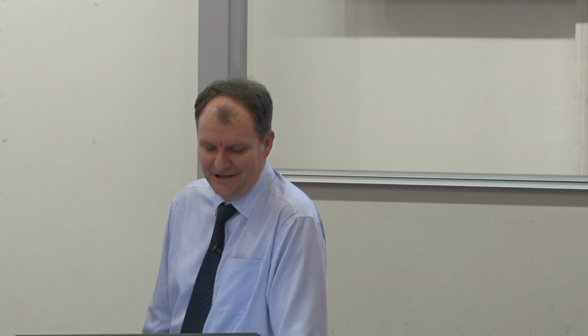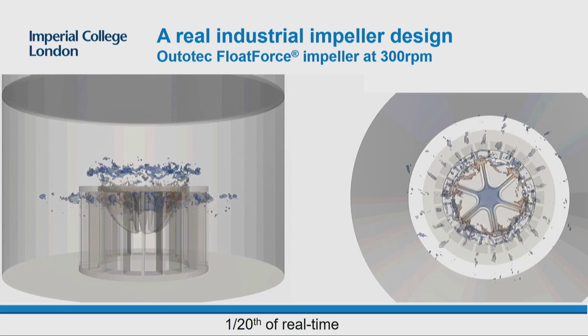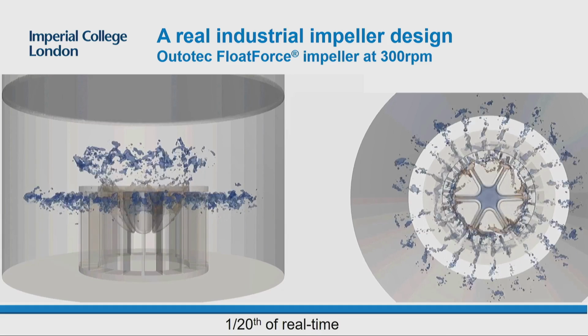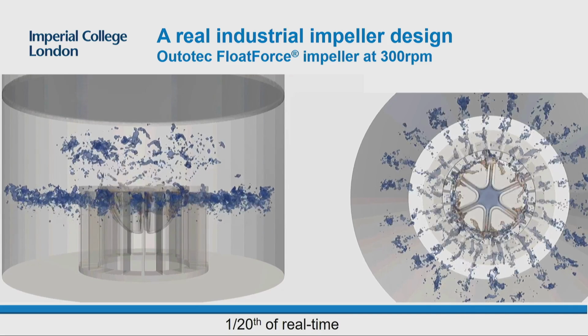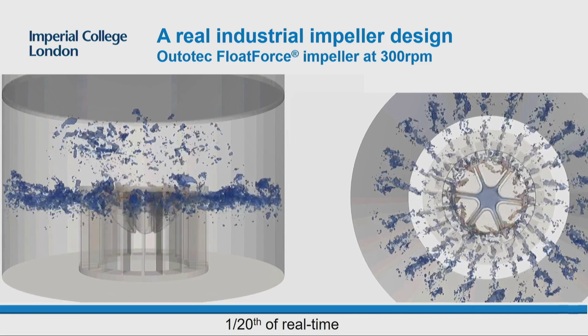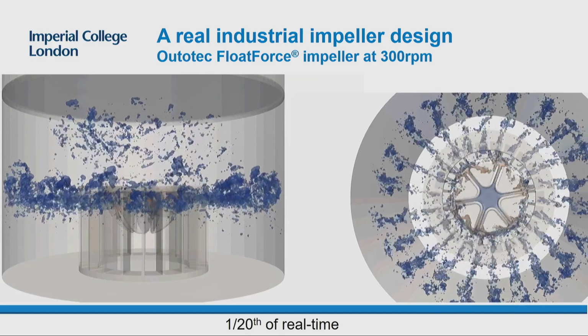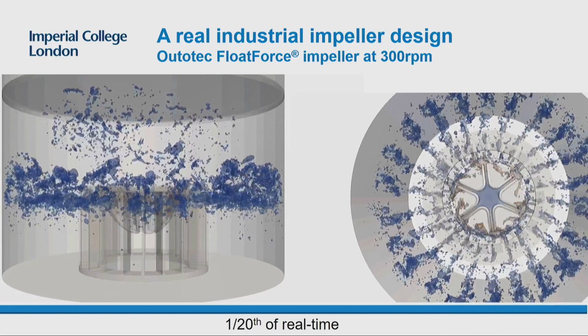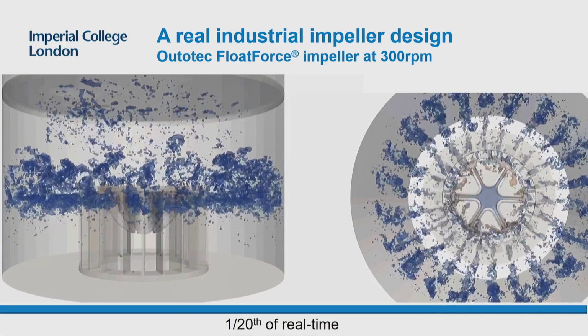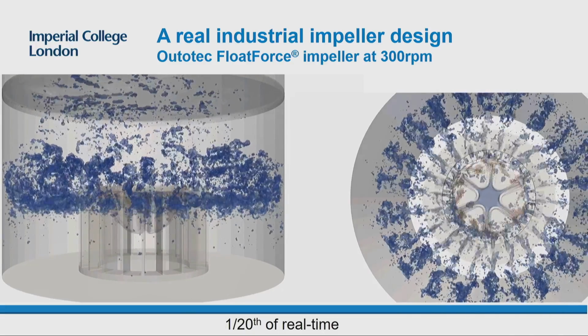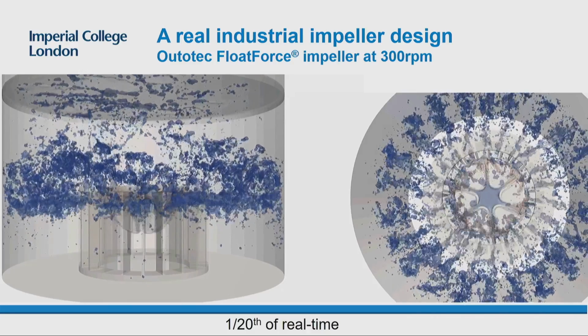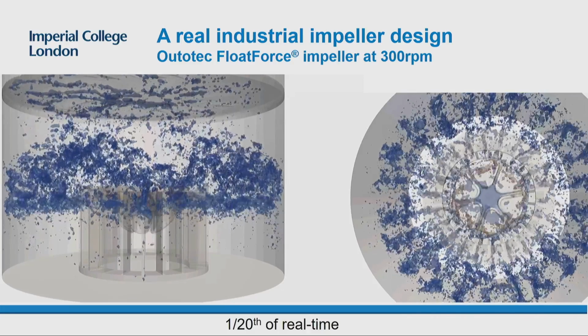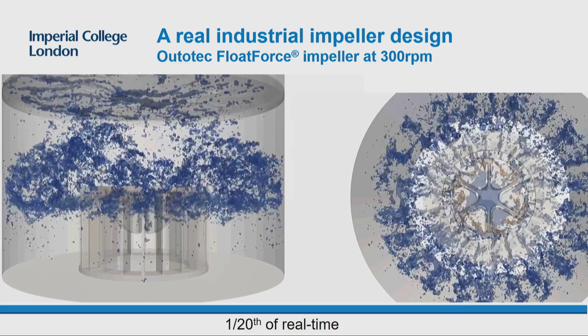So this is just showing the same simulations, but slowed down. Looking from the bottom, you can see how the spinning impeller and the stationary stator cause the shear forces which actually cause these bubbles to break up. In fact, some of them don't break up quite there, but it causes the bubbles to become elongated. And as soon as you have an elongated bubble, there's the Rayleigh instability, which means they'll pinch off into a set of droplets, which is the same thing you get with a water tap. If you turn it on, it'll come down and eventually pinch off into droplets. Same with bubbles. You stretch them out, they'll pinch off into bubbles.